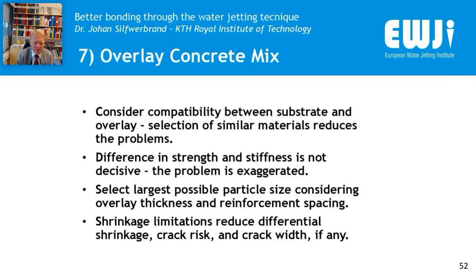Another thing is about the overlay concrete mix. Consider compatibility between the substrate and the overlay. Selection of similar materials reduces the problems. Similar repairs with similar materials, or like with like. Likewise, that is a rule of thumb. Difference in strength and stiffness is not decisive, however. The problem is exaggerated, but still I think it is good to use concretes of similar types. Select the largest possible particle size in your aggregate, considering overlay thickness and reinforcement spacing. But it is as large as possible, because if you have larger particles of your aggregate, it will shrink less. And shrinkage limitations reduce differential shrinkage, crack risk, and crack width if there are any cracks.